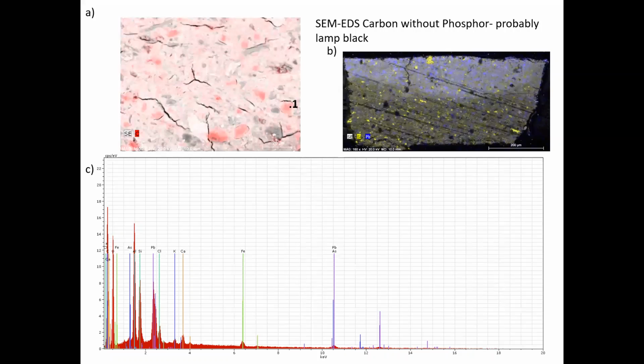This suggests that the painter was possibly aware that bone black, mostly used as colorant in artists' painting, should not be used in mural painting because it causes a fluorescence. This fact is still respected nowadays in the making of Indian mural paintings by using lamp black. So by this use of lamp black, we can make a connection to mural paintings. Was this a mural painter? We still don't know, but we can put forward this possibility.